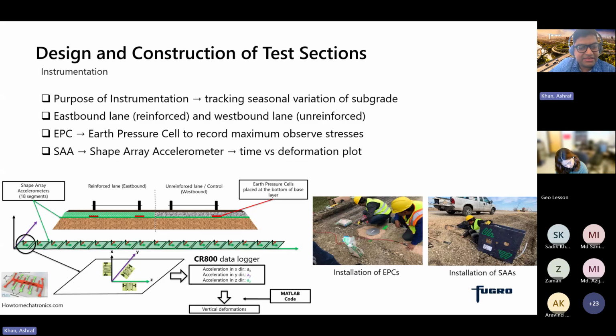It had like 18 segments, and all the segments had the sensor to capture the tilt angle. The tilt angle can be used to measure the deflection. So it can collect the data in any frequency. For this current purpose, we have used like 15 minutes interval. So lots of data were collected from this shape array accelerometer to check the movement of the expansive subgrade with time.